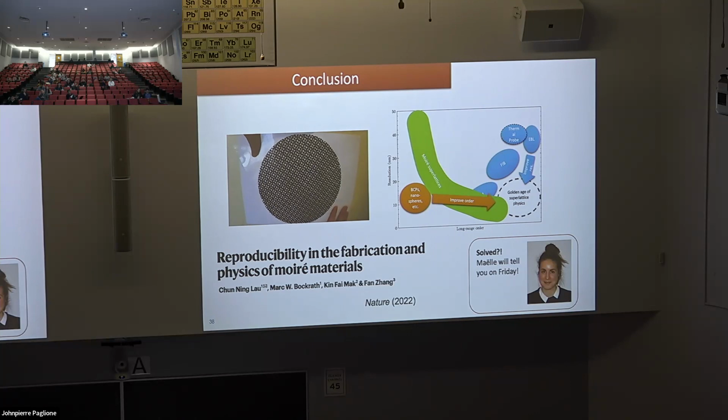As Jim showed, you have this exfoliated 2D material on your surface, and then you come in mechanically with another 2D material. You just make it stick to that 2D material. You rotate, make another part stick to that 2D material, and any strain or disorder from the graphene, for instance, on silicon oxide, to some degree gets translated onto the BN. In this low twist angle regime, there's also a lot of friction that helps pin any disorder that you start out with.